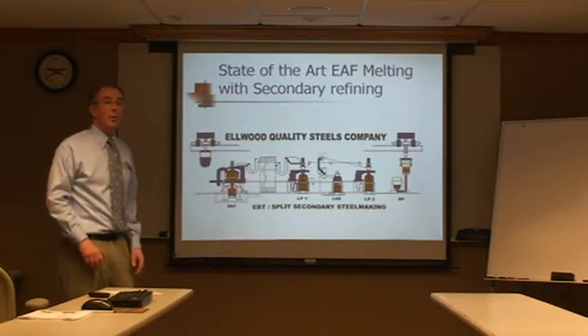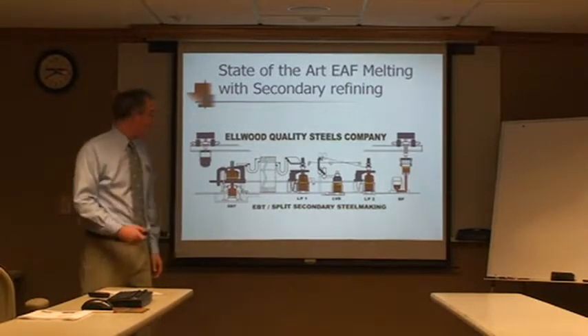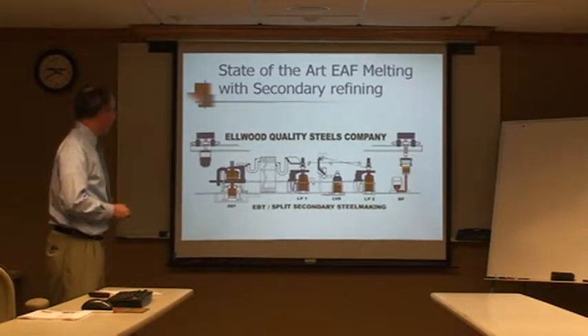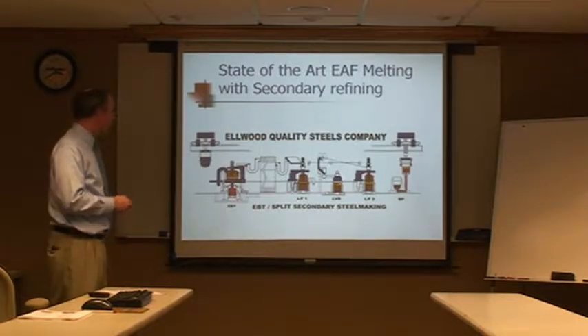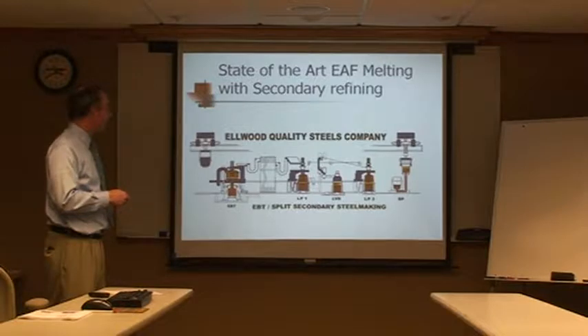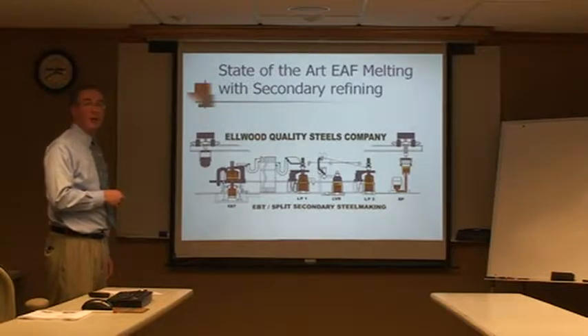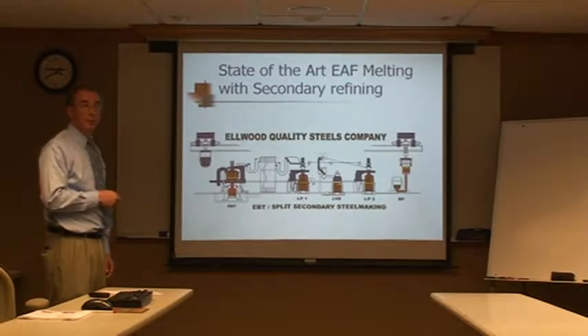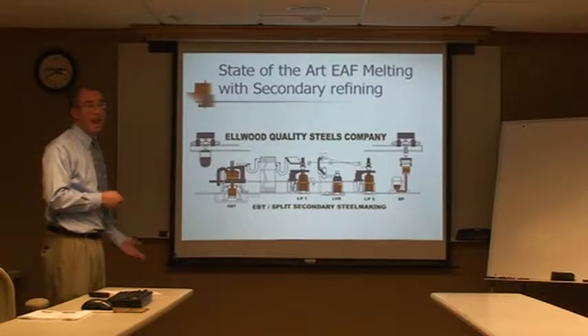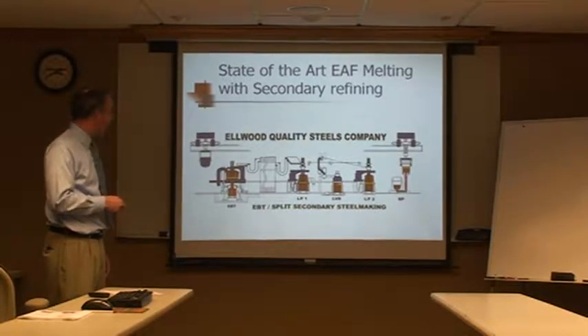This is an overview of the process at EQS. We have what we were just talking about. We have the primary melting, which is in the electric arc furnace here. Here we start with charging of the scrap. So there's a scrap bucket that loads the scrap into the furnace. We melt this, going from scrap to liquid as fast as we can, tapping the liquid steel into a ladle.